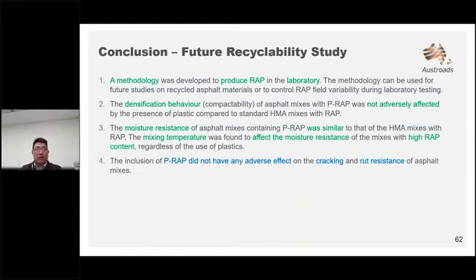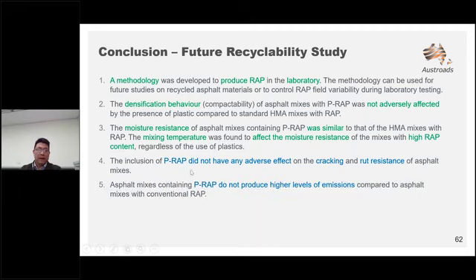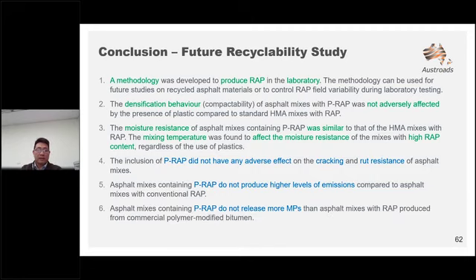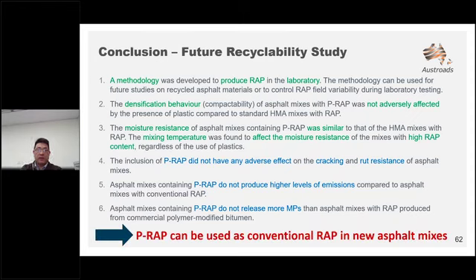In overall, the inclusion of PRAP didn't have an adverse effect on the cracking and rutting resistance of asphalt mixes. We also found that the asphalt mixes containing PRAP do not produce higher levels of emissions compared to the asphalt mixes with conventional RAP. And in terms of microplastics, it was found that the asphalt mixes containing PRAP also did not release more microplastics than asphalt mixes with RAP produced from commercial polymer modified bitumen. So overall, it is concluded that PRAP can be used as conventional RAP in new asphalt mixes. So now I hand it over to Filippo.